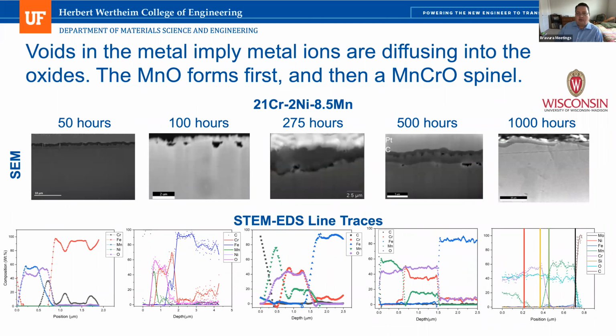We've done SEM on samples from various amounts of oxidation time. And one thing that stands out is we see the oxide layers forming, but we also see the formation of voids. And the voids are forming at the metal oxide interface. So this seems to imply that we have metal ions that are actually leaving the metal, transporting through the oxide, and then reacting with the oxygen, and that's what's causing the growth of the oxide layer.